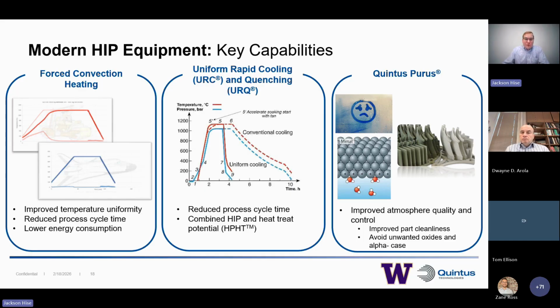Quintus also has uniform rapid cooling and uniform rapid quenching capabilities. The quenching technique used within a Quintus system has a cooling rate faster than that of an oil quench, slower than that of a water quench. So here we can quench and cool the system significantly quicker than conventional cooling, which allows again for that reduced process cycle time, but also the opportunity to use high pressure heat treatment that I will discuss here in a minute.